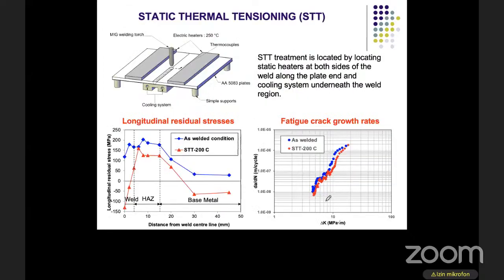So I would like to show you some results of my research, which are a collaboration between my university, UGM, Gadjah Mada University, and BRIN. First, we developed STT treatments, where this treatment is performed by locating two static heaters at both sides of the weld along the plate length. This is the plate length, and at the same time, the weld region beneath the weld is cooled by a cooling system, which consists of water flow.